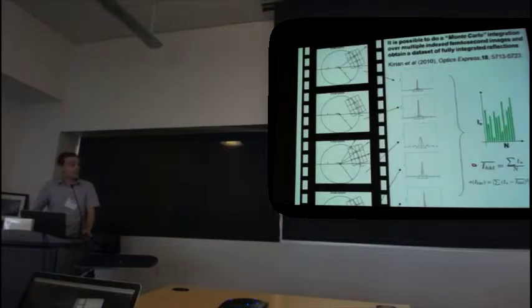But despite all of the variations in the parameters that affect the measured intensities from your experiment, as has been shown, as John said before, if all of the variations are independent from each other and random, and if there is no systematic error in there, the arithmetic mean of a sufficiently large number of measurements or observations will approximately correspond to the true and fully integrated reflection, which in our case is called the Monte Carlo integration.